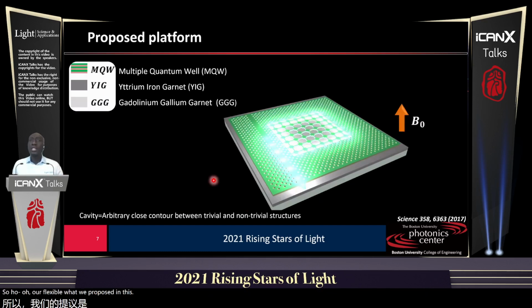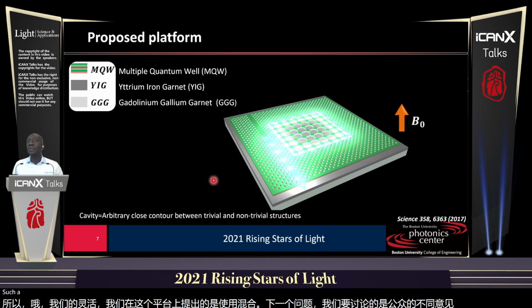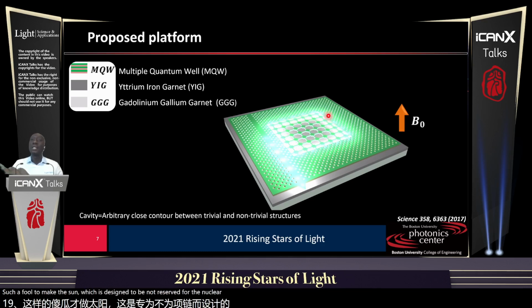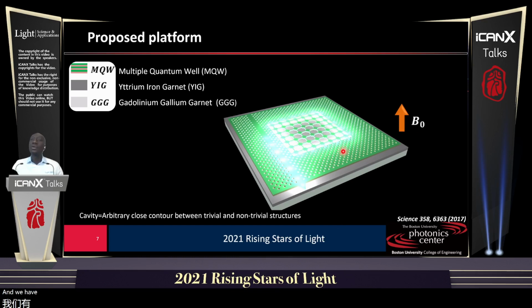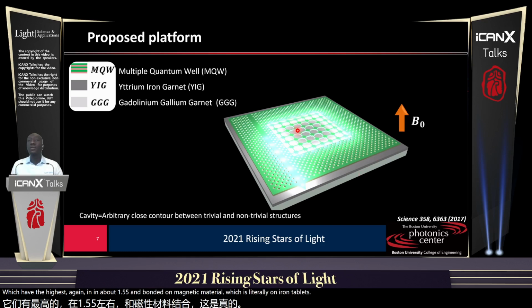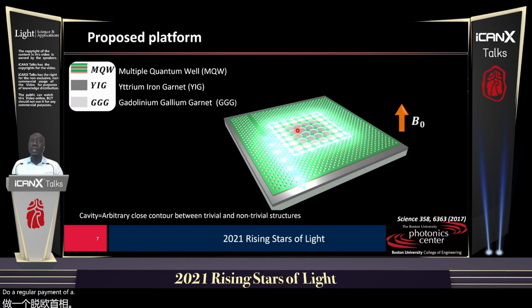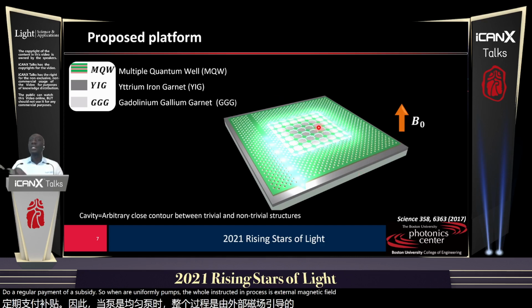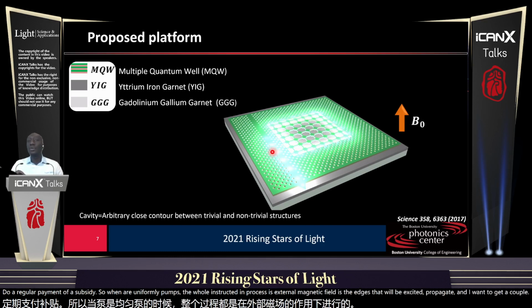What we propose in this platform is to use a hybrid photonic crystal, where we have two types of photonic crystal. A star-shaped photonic crystal, which is designed to be a non-trivial photonic crystal, is inside the cavities. And we have an arrow-shaped photonic crystal, which is designed to be a trivial photonic crystal, the photonic crystal of the cavities. Both of them are made in InGaAsP, which has the highest gain around 1.55, and bonded on a magnetic material, which is yttrium iron garnet, to break the time reversal symmetry. So when we uniformly pump the whole structure in the presence of an external magnetic field, the edge state will be excited, propagate, and eventually couple to the waveguide, which consists just of removing one line of the trivial photonic crystal.